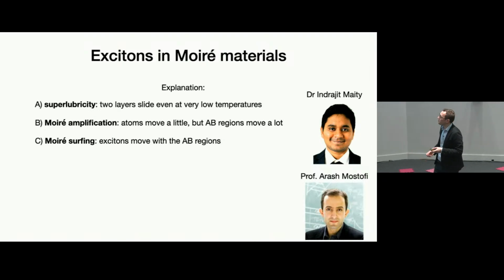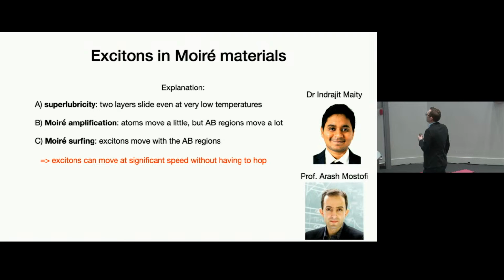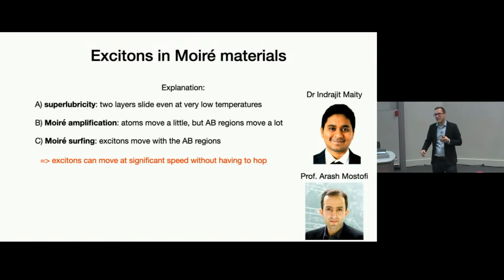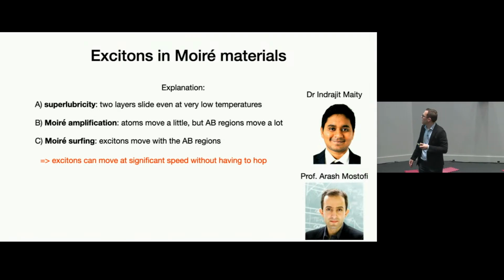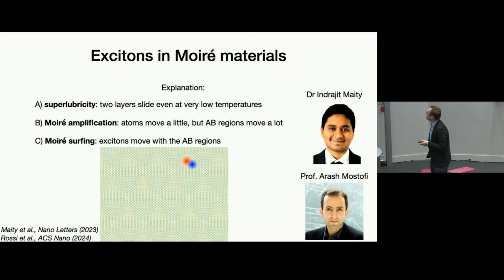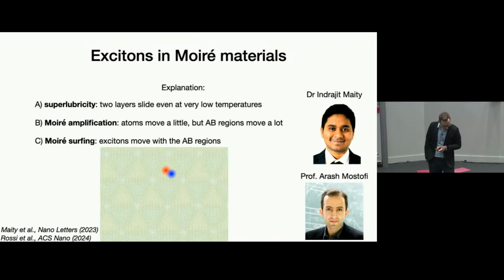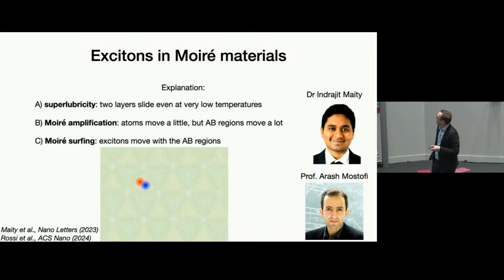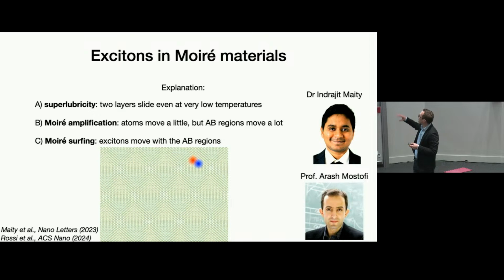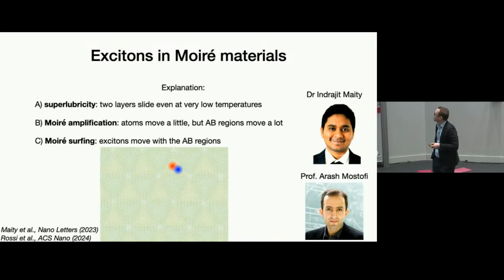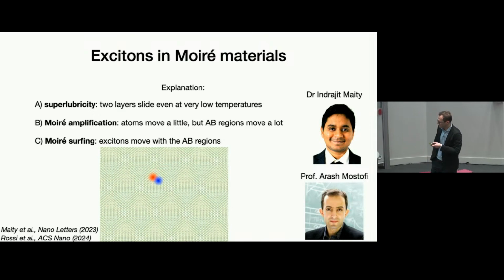The excitons actually move along with the AB regions. So if we take these three things together, what it means is that the excitons can actually move at a very significant speed without ever having to hop over the mountain. And to convince ourselves that this hypothesis is actually true, we carried out a computer simulation of the Moiré semiconductor at a finite temperature, and you can see the exciton move around.